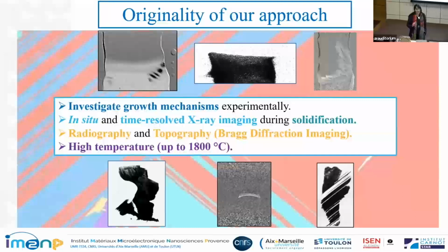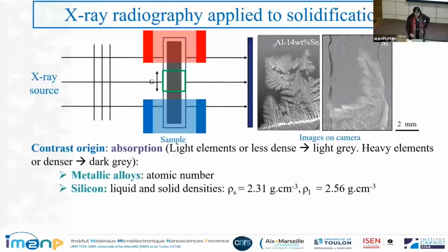So what is the originality of our approach is that we investigate these growth mechanisms using in situ and time resolved X-ray imaging during the solidification, and we use two techniques, radiography and topography, at high temperatures up to 1,800 degrees C in our furnace. So first, or at the same time, we perform X-ray radiography together with topography. So how do we do? I will briefly present these methods.